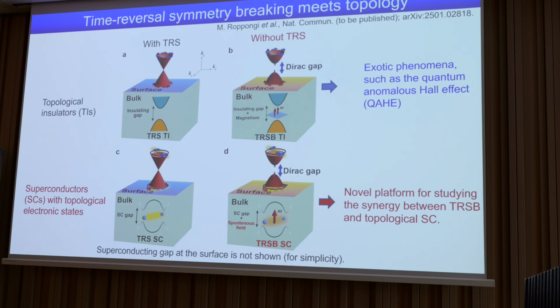So a similar situation can happen in superconductors, where you can actually have a topological surface state. But here we have a time reversal symmetry breaking superconductivity inside the bulk, and you create the Dirac gap at the surface, so you may have a completely different new kind of situation.